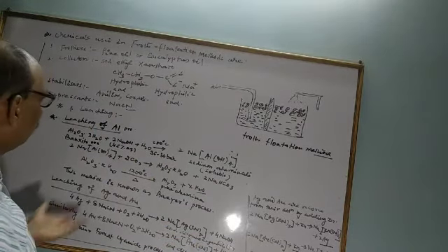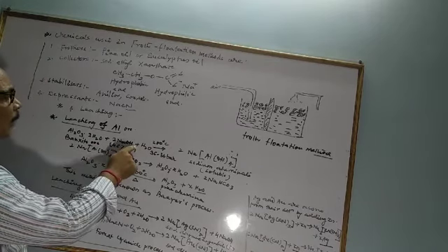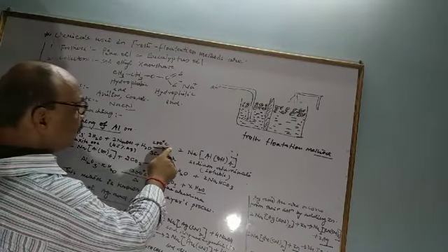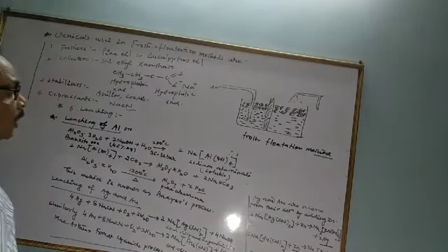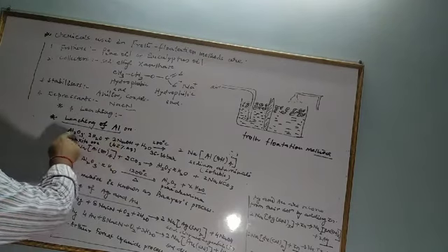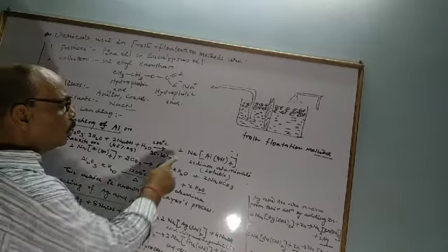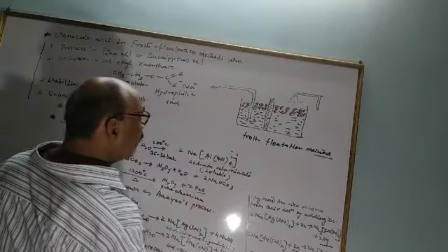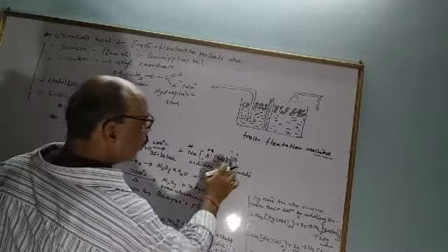How is it possible? Say for example, in the case of aluminum, the chief ore of aluminum is bauxite. Bauxite is first treated with 45% aqueous solution of NaOH at 200 degrees Celsius and 35 to 36 bar. What happened? Aluminium is an amphoteric metal. It reacts with sodium hydroxide and forms a soluble complex salt called sodium aluminate, Na[Al(OH)4]. Why 4 OH? Aluminium has +3 charge and sodium has +1 charge, so there are 4 hydroxides.